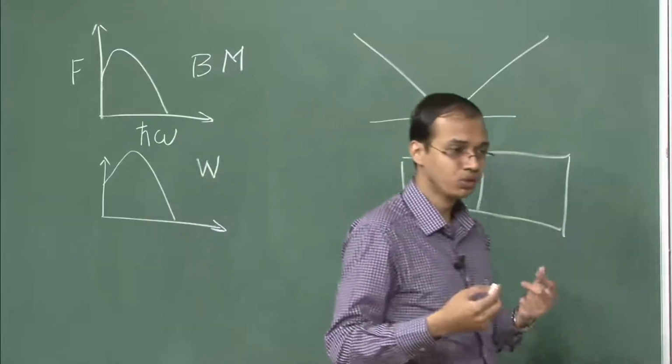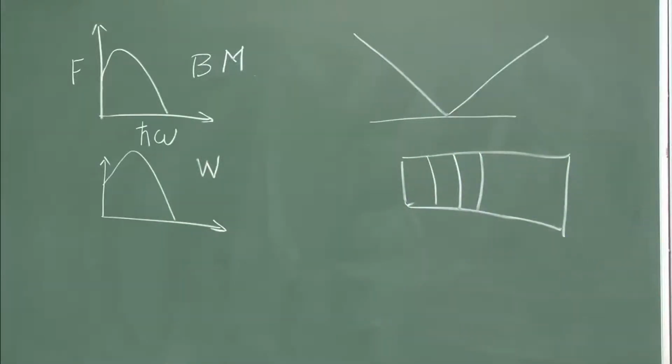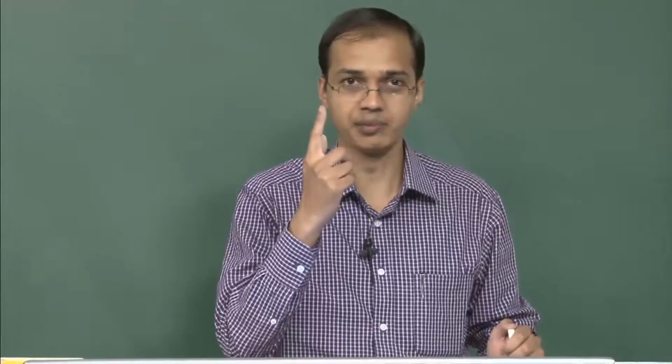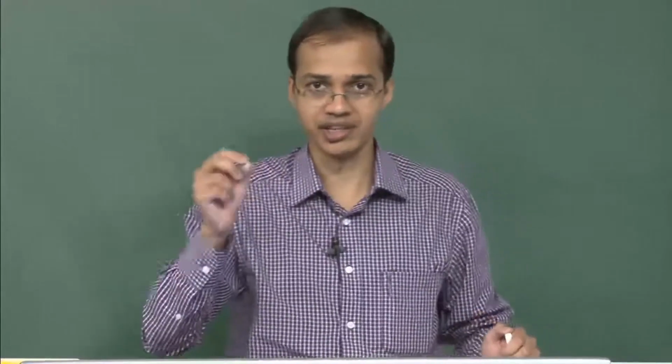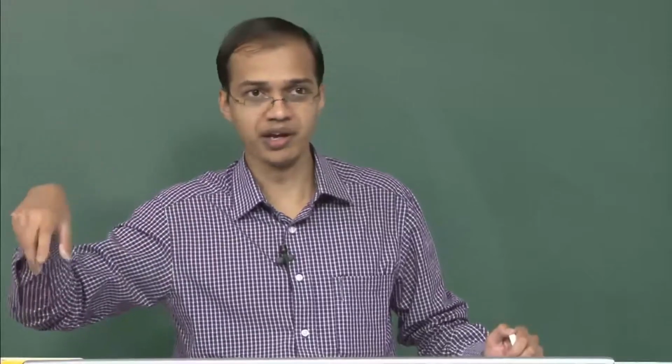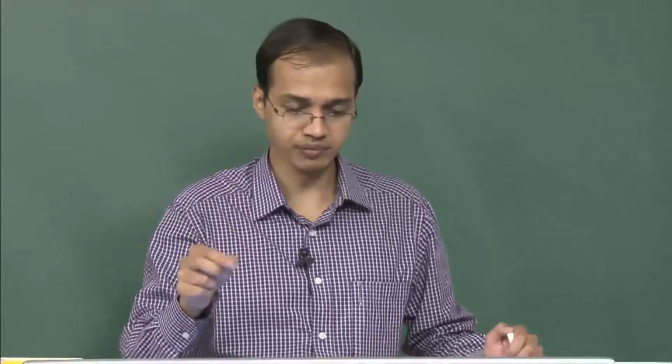Now, I will go back and show you the state of the art detectors which can count the X-ray signal and convert it to an electronic signal. We have what is known as a single photon detector, which reads only one theta or one angle at a particular time. This comprises the normal scintillation detector made of sodium iodide, where on hitting the X-ray we get the emission of a photoelectron, which is then passed through a photomultiplier tube to generate an electrical signal, proportional to the number of X-ray photons hitting the sodium iodide